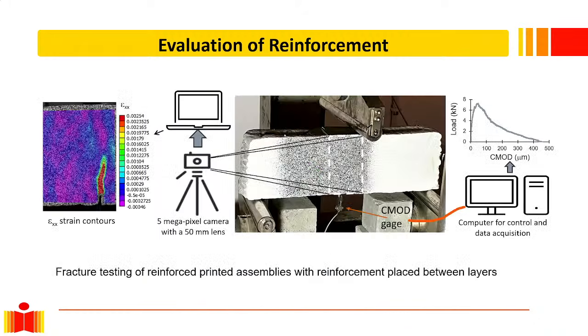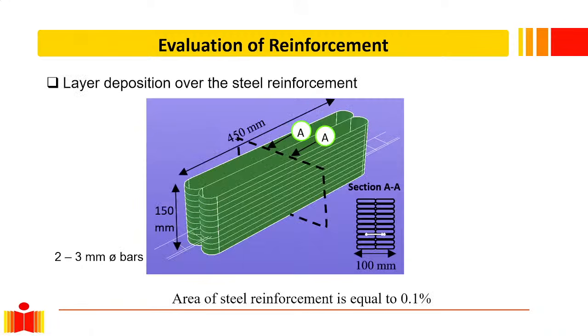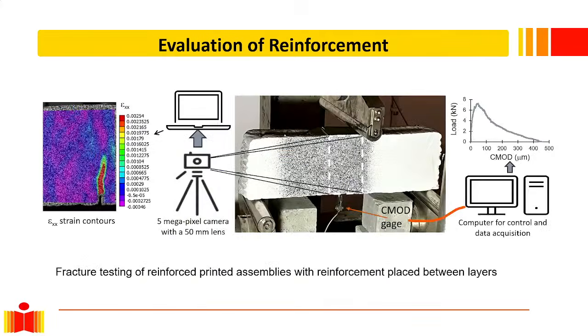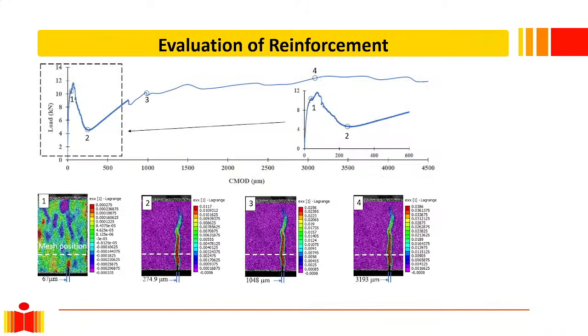And so we did some fracture tests on these beams that are printed with the steel placed between two layers. Here you can probably see, there's a notch, and the steel was placed at this level here. We did the fracture test, and from the fracture test we basically extracted this load response, which is not very encouraging, but there is still something we can salvage from here.